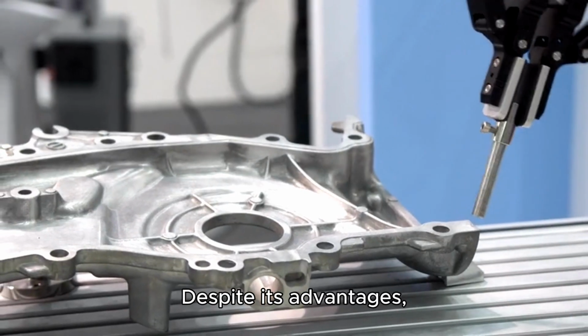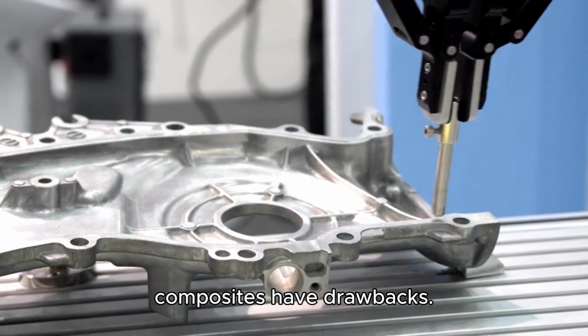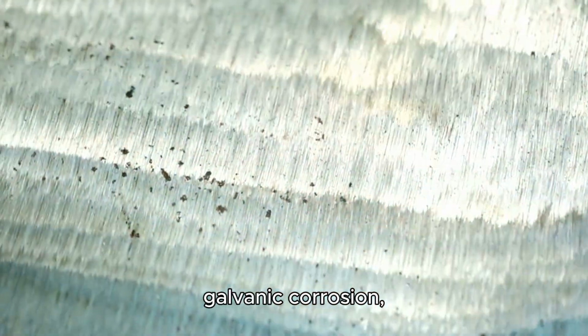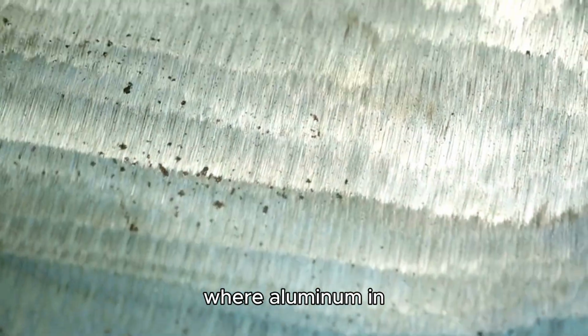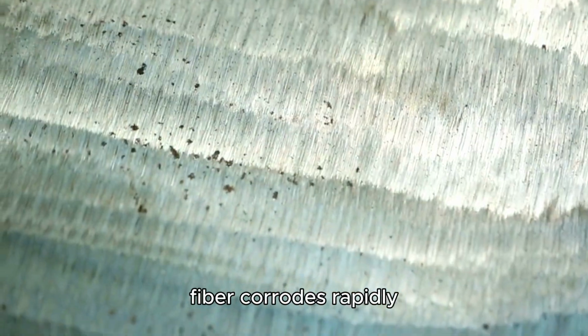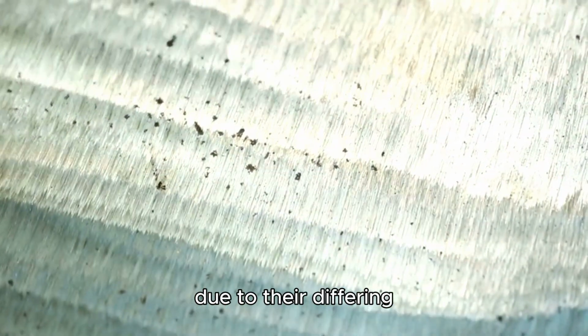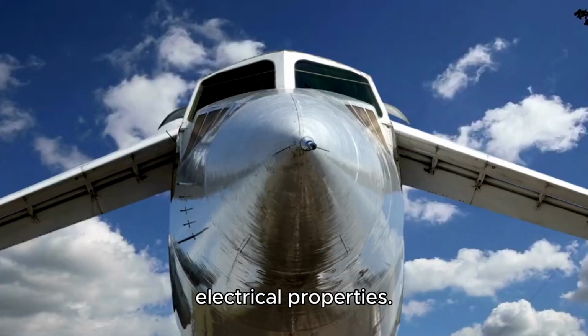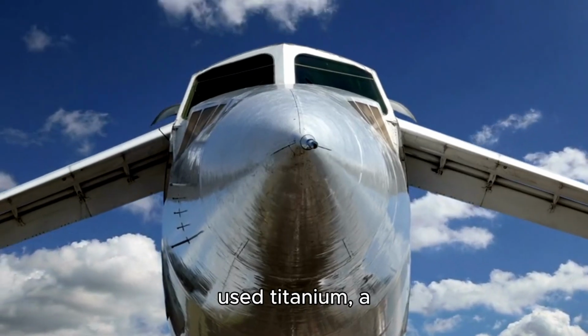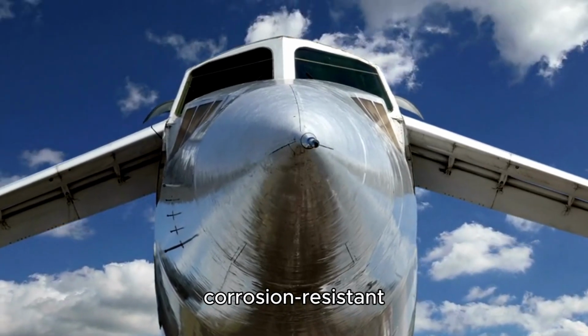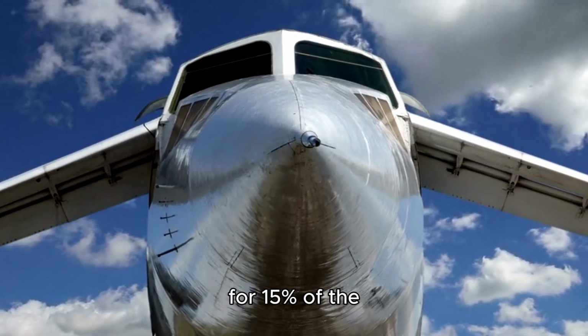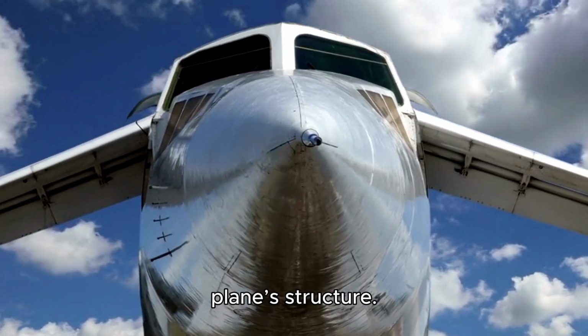Despite its advantages, composites have drawbacks. One significant issue is galvanic corrosion, where aluminum in contact with carbon fiber corrodes rapidly due to their differing electrical properties. To avoid this, Boeing used titanium, a corrosion-resistant but expensive metal, for 15% of the plane's structure.